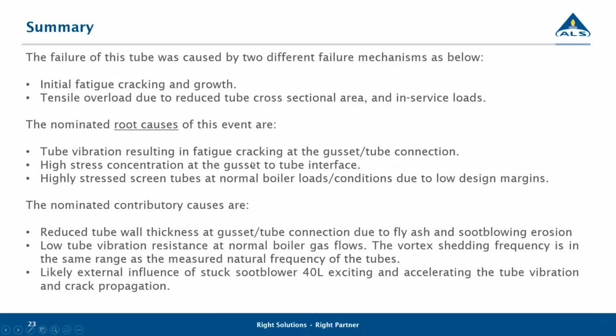So just in summary, the failure was caused by two different failure mechanisms. The one was the initial fatigue cracking and growth, and then the tensile overload with the reduced cross-sectional area. The nominated root causes of the event were tube vibration resulting in fatigue cracking at the gusset tube connection, high stress concentration at the gusset to tube interface, and highly stressed screen tubes at normal boiler loads and conditions too, which doesn't have a big design margin.